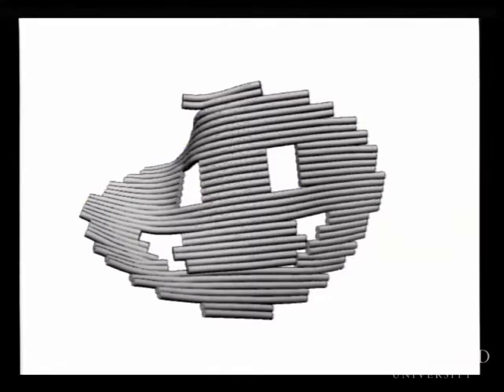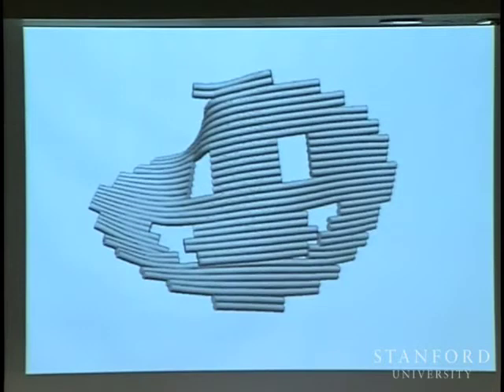So now in the second generation structures, we just pay a little bit more attention to the twist of these structures, and you can get them quite flat over large regions. But this may also contribute to why that smiley face looks so broken up, because when he's sticking to this very sticky surface, if part of him sticks and then the other part sticks and he folds over, because his nose is so distended and his jaw is bent back, maybe that gives you some of those screwed up structures, but we're not sure. But that's at least a hypothesis you can entertain.